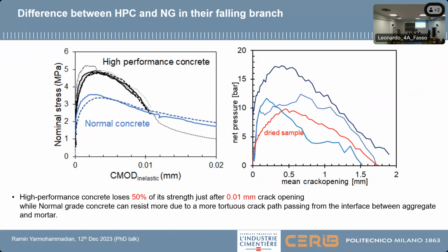So another thing that I wanted to mention today is, as I mentioned, high performance concrete is really sensitive to spalling, while normal concrete is not. Another reason that I can mention is here. So you see in high performance concrete, after 0.01 millimeter, we lose 50% of the resistance of the concrete. So the concrete will lose mostly all of its strength when it is cracking. But when we are using normal concrete, it's not the case. So we still have resistance of concrete which is working. So the concrete can still resist direct tensile stress, which is another advantage of normal concrete in spalling, I would say.